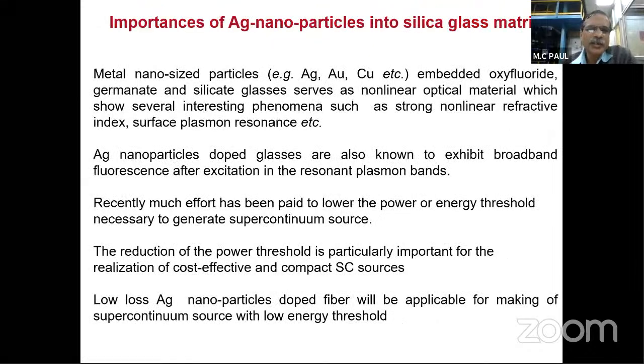Importantly, metal nanoparticles in optical fiber, in different glasses and not only germanium silicate glass, give rise to highly nonlinear optical properties, showing a strong nonlinear refractive index and also surface plasmon resonance. The purpose is to use this kind of fiber to make a broadband supercontinuum source in the visible under a suitable pumping scheme, and the fiber also shows a low energy threshold.